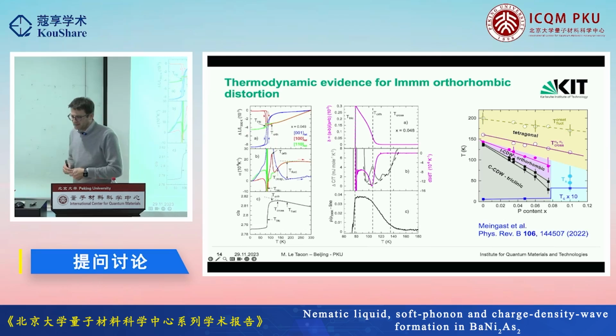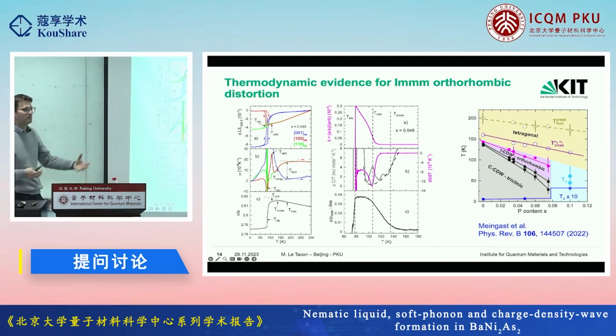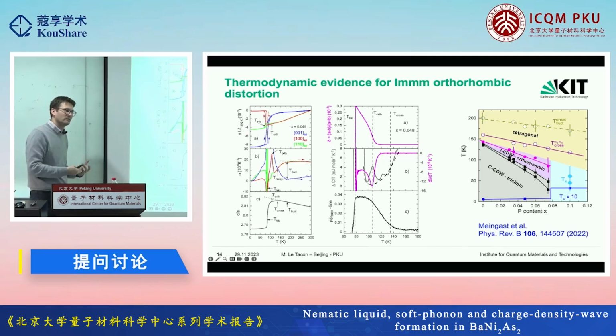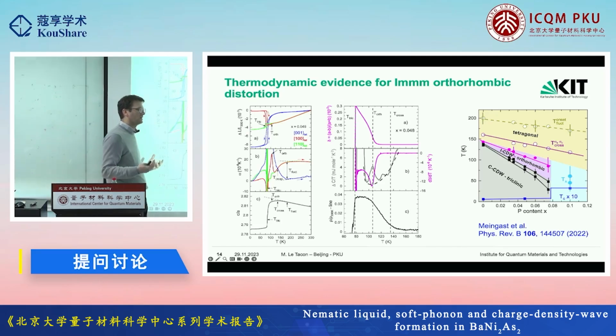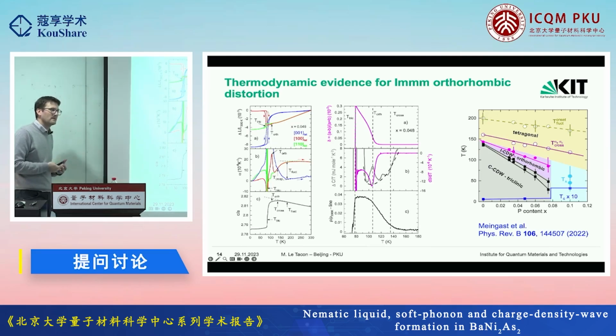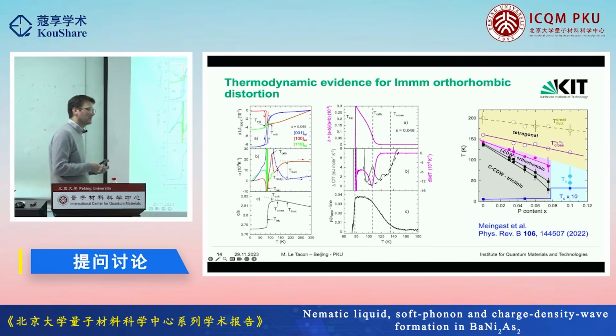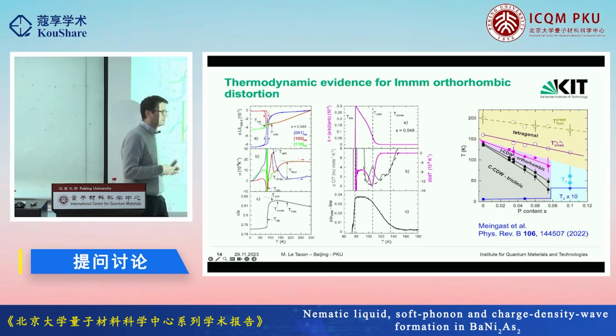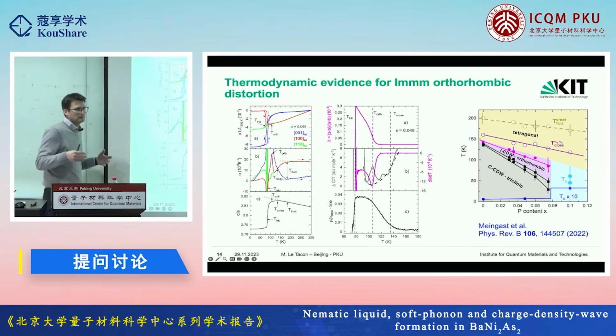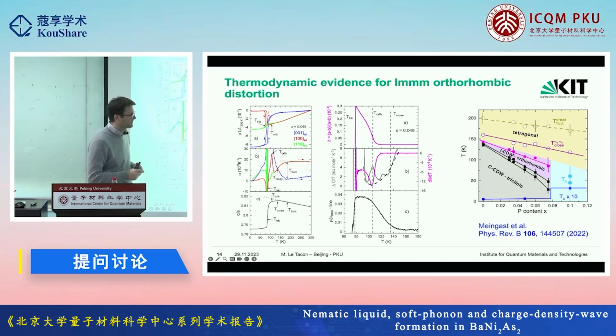I don't know. It seems that all that nematicity in that case is really carried and driven by the phonons, more than by the electrons. So the electrons are somewhat following the phonons here, but do not seem to be the main driver of this nematicity. That's also what's suggested by the elasto-resistance measurement, which does see a signature of a B1g nematic fluctuation, but nothing which is critical, and that would be associated, for instance, with unconventional superconductivity at low temperature, and also nothing that is really strongly involving the electronic degrees of freedom.